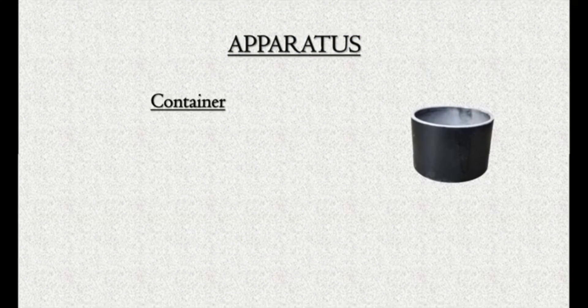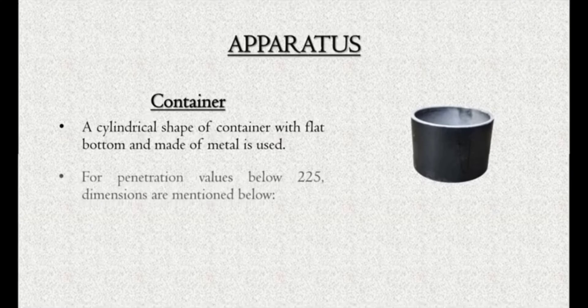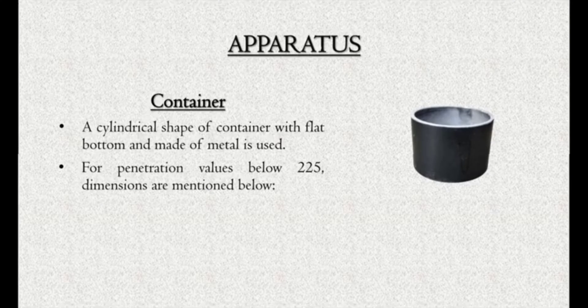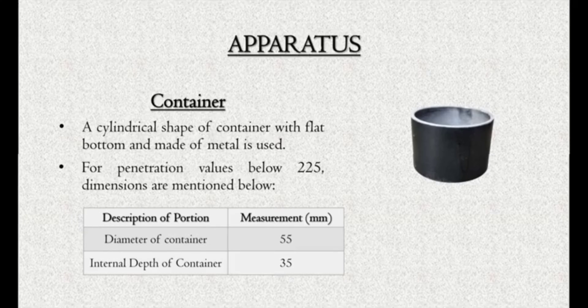Container: A cylindrical shape of container with flat bottom and made of metal is used. For penetration value below 225, dimensions are mentioned below: Diameter of container 55 mm, internal depth of container 35 mm.